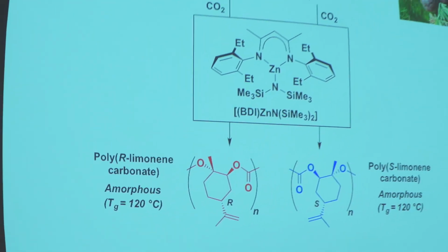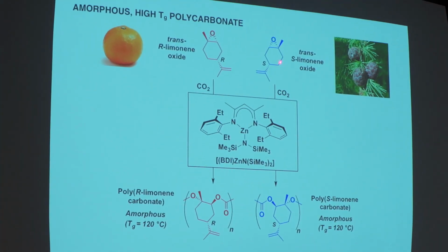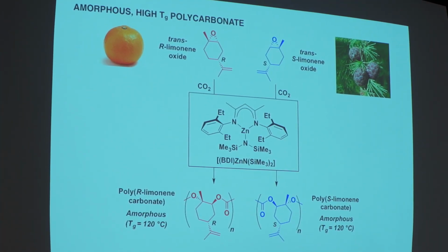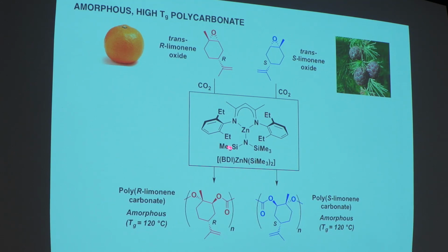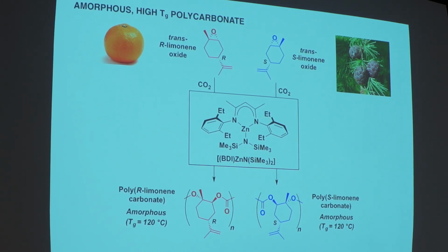And so I want to show you some neat things with the stereochemistry of this polymer. So from oranges, you can get the R isomer, and from various types of pine trees, you can get the S isomer. So these are now mirror images of one another. And this is a modified version of our catalyst that takes CO2, and the R gives poly-R-limonene carbonate, the S gives poly-S-limonene carbonate. And as you'd expect, the properties of these polymers, except for how they rotate plane polarized light, are identical because they're just mirror images of one another.